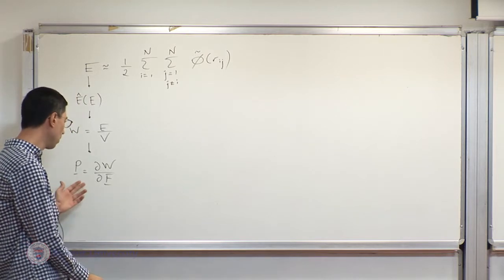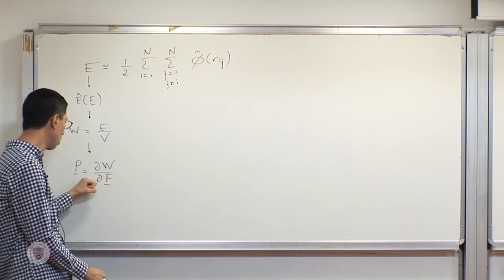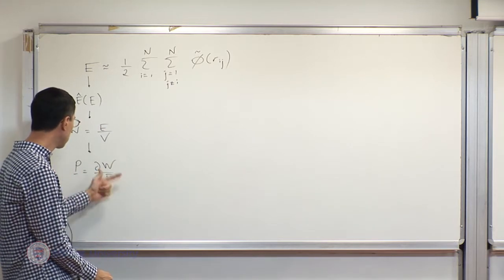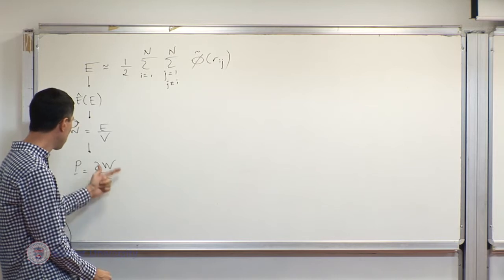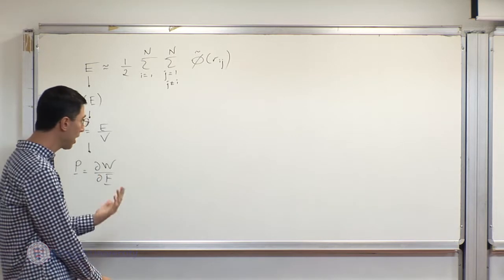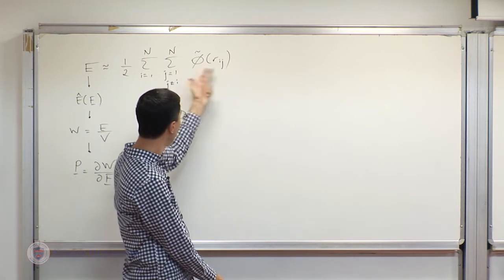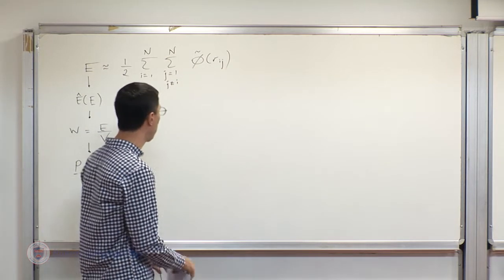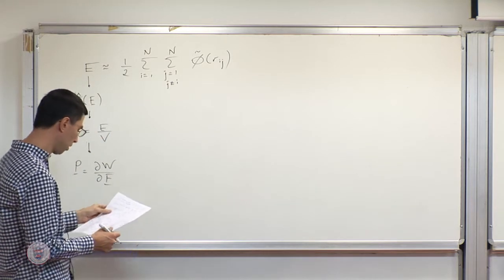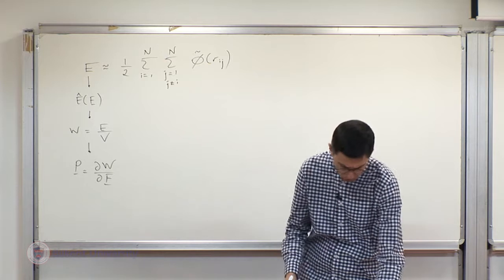One advantage and the goal of this topic is to highlight how some parameters appearing in the expression for the strain energy can actually be deduced implicitly from what you have invoked as your pair potential. So it's somewhat of a non-phenomenological approach, at least on the macro scale.